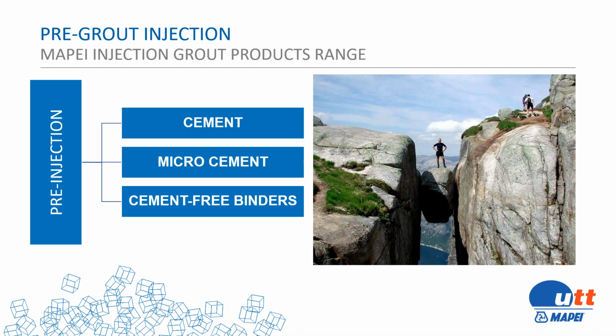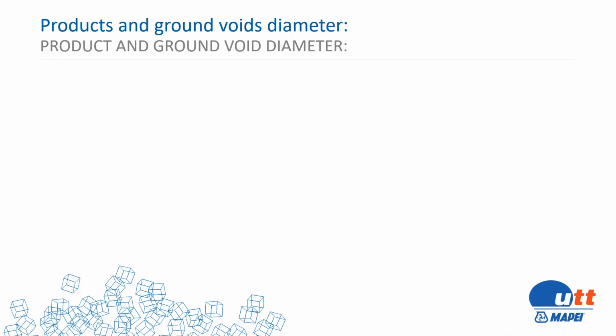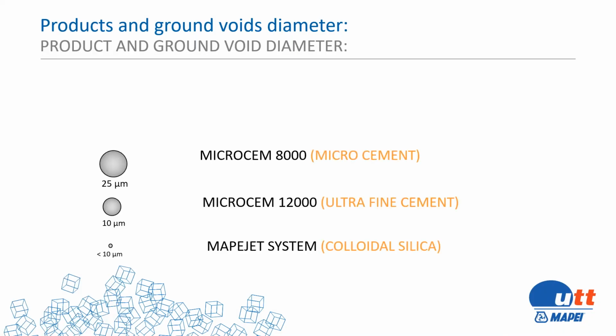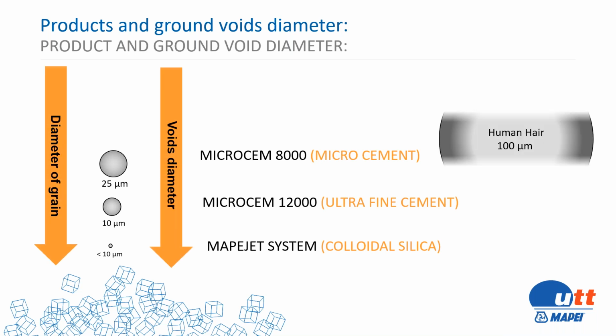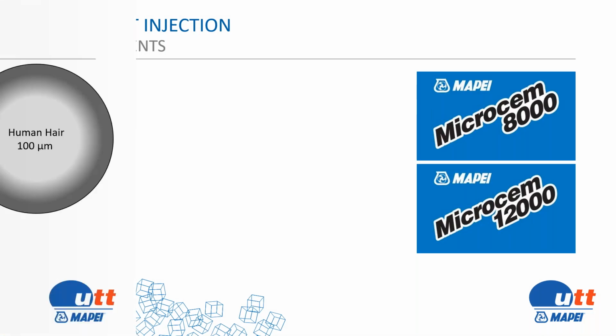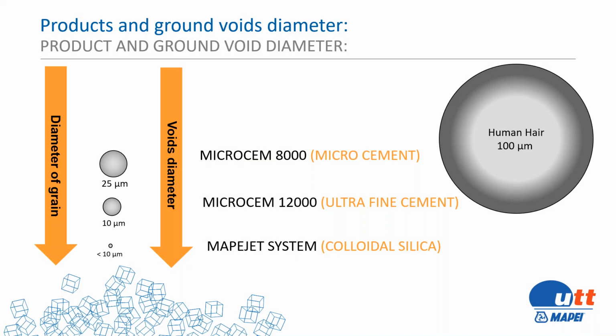At MAPEI UTT, we offer the microfine cements and the cement-free binders. When we look at the grain size and the void diameters in this chart, we have on the very bottom our MAPEJET system, which is a colloidal silica. Then our MicroCem 12000 is an ultra-fine cement, and then our MicroCem 8000. So what you have is grain sizes. If you compare it in size to the human hair, you can see that a strand of human hair compared to our microfine cement makes it very, very low viscosity and has great pumpability.